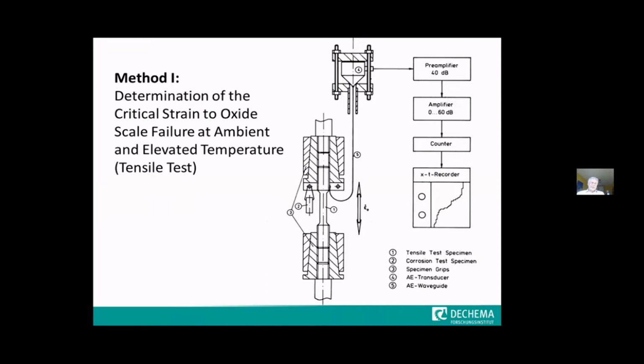Now, the first method that we used in the old days was that we just took a tensile test specimen, like here, in a tensile testing machine, and then we spot welded a platinum wire to the specimen and had some, I would call it microphone, an acoustic emission sensor attached to this platinum wire. And the whole thing could be done in a furnace, so we could measure acoustic emission even at high temperatures. And since the metal substrate itself is quite ductile, this leads to a very different type of acoustic signals than the brittle oxide, which is formed on this metal by oxidation.